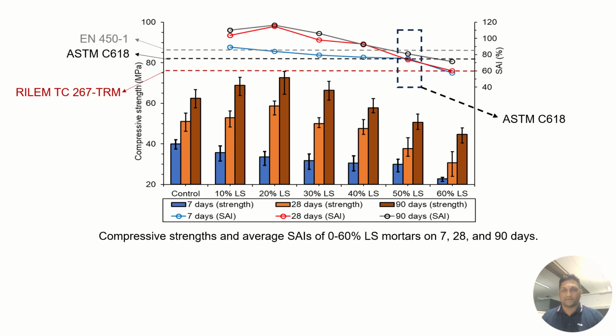It is seen that the 50% lithium slag incorporated mix still satisfied the requirement set by ASTM for 75% SAI at 7 days and 28 days, British standard at 85% at 28 and 90 days, and RILEM 65% SAI at 28 days.